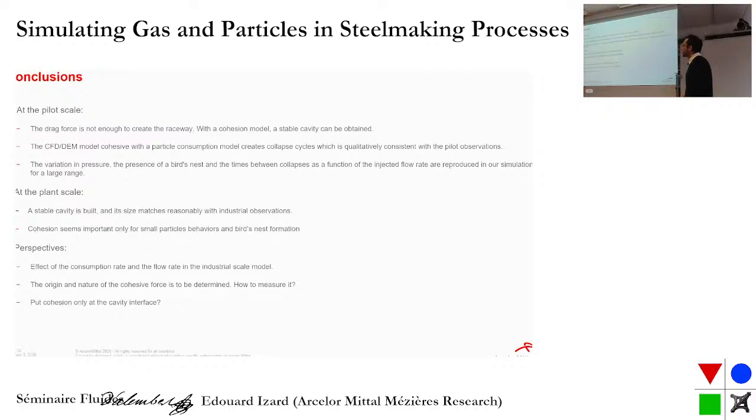So what we have shown at the pilot scale is that the drag force is not enough to make the raceway stand. We need a cohesion parameter to have the balance, and we have developed a quite simple consumption model to reproduce the experiments qualitatively. We have good overall results comparing to this experiment. At the plant scale, we have a stability of the cavity, and it matches reasonably well the industrial observation.